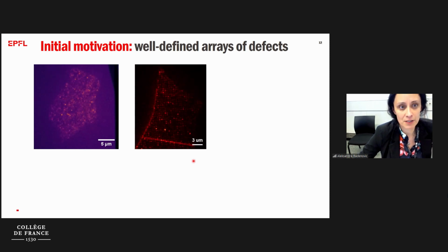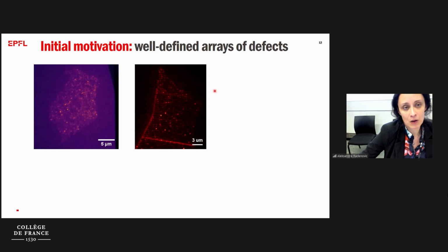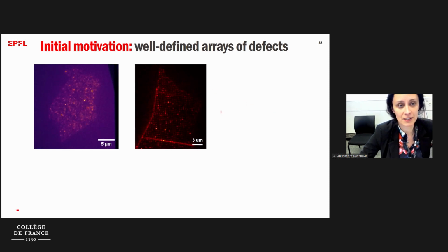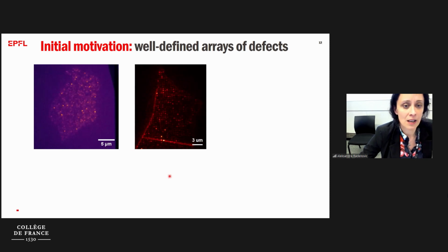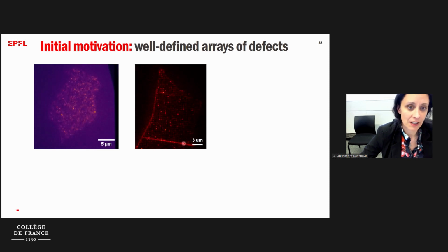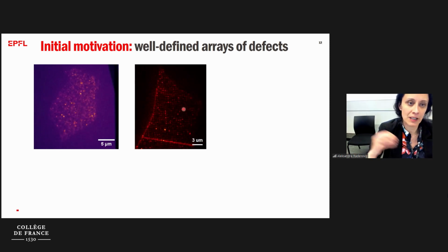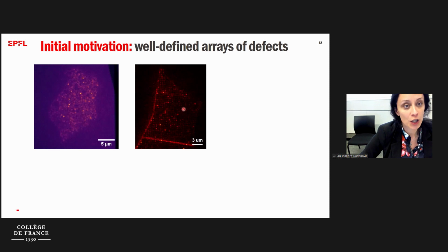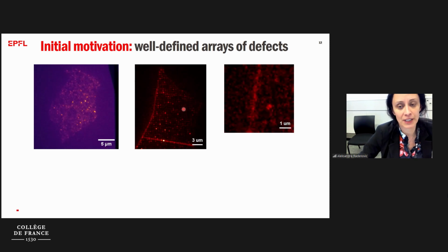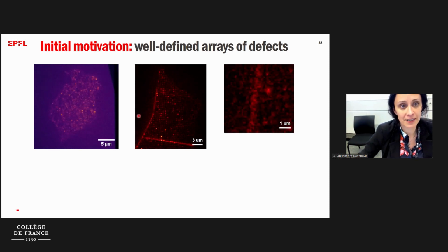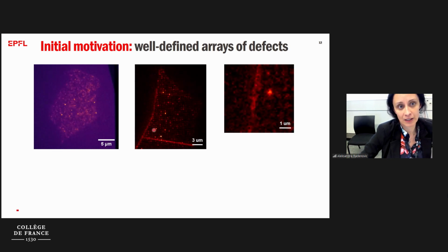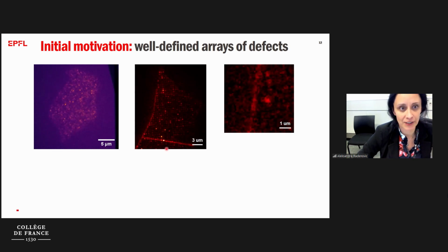So we started first by using an ion beam, a xenon ion beam, writing initially this kind of checkerboard pattern, hoping that if we move down in the spacing of these patterns, we can reach the hopping length that we have observed in these stochastically induced defects in hexagonal boron nitride.